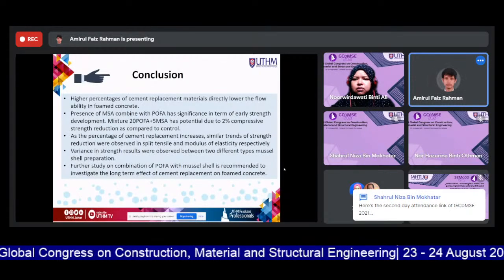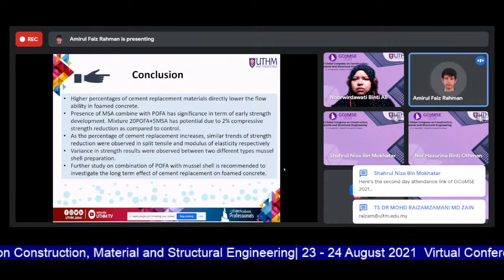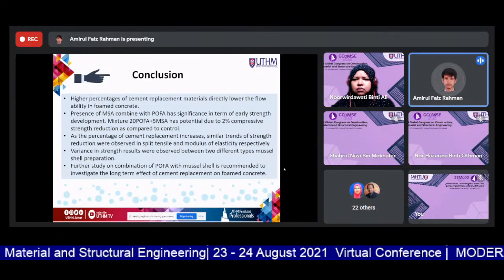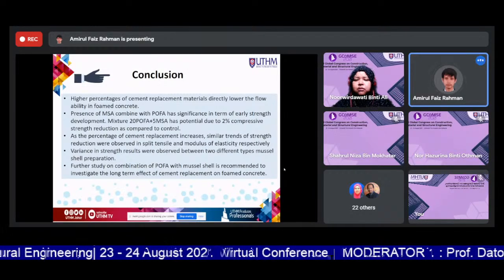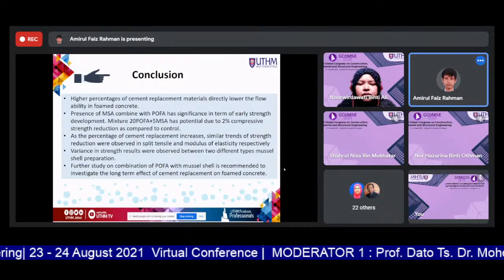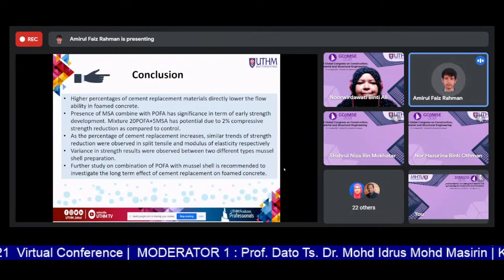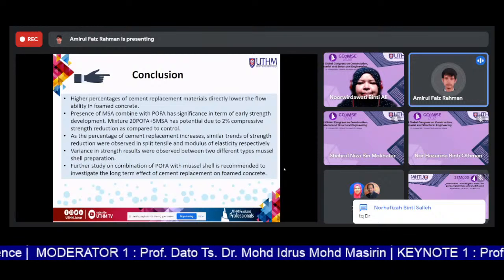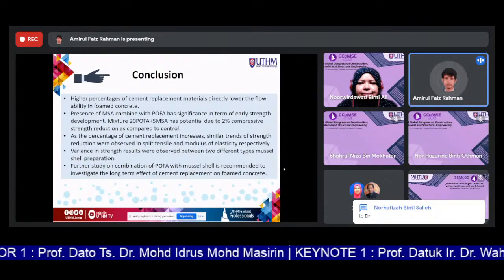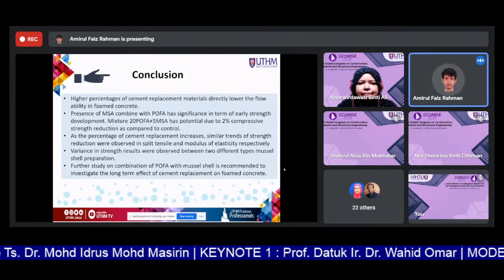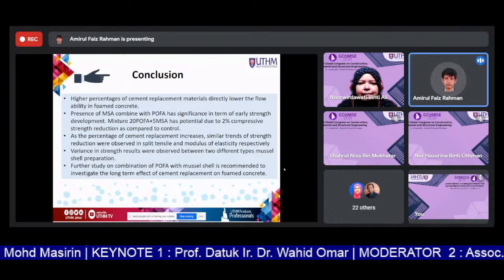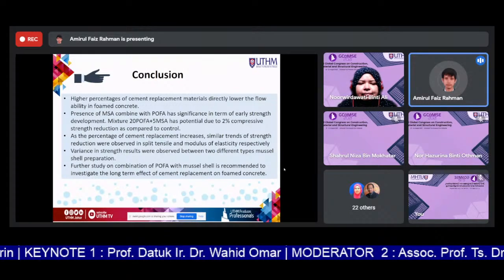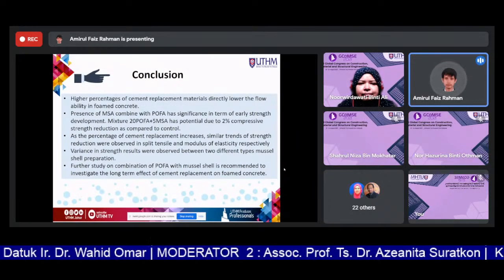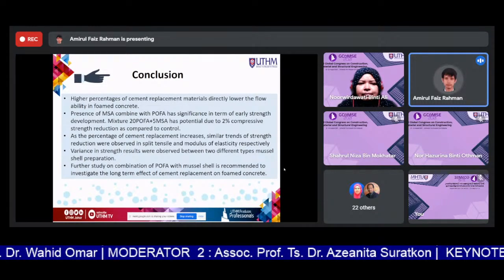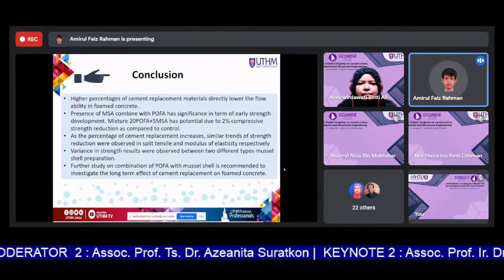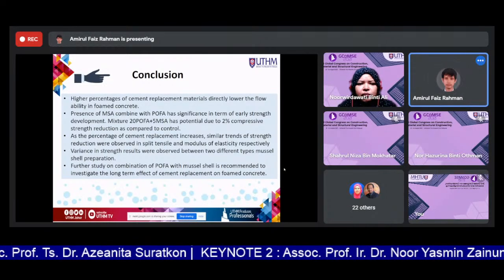For the conclusion, a higher percentage of replacement material directly lowers the flowability of foam concrete, and the presence of POFA combined with MSA shows some potential in terms of early strength. And the mixture 20% POFA and 5% MSA has the highest potential due to only 2% variation as reduction compared to the control. As the percentage of cement replacement increases, similar trends of strength reduction were observed in both split tensile and modulus of elasticity.